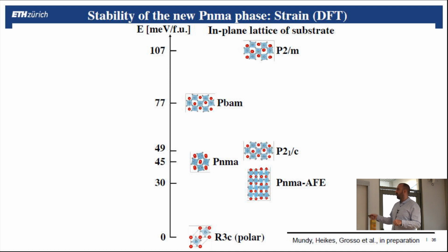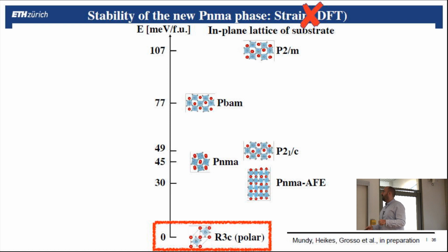And you can see that this is still the lowest energy according to the strain, but there is this phase that is the lowest one above this polar ground state. But that means that the strain is not explaining why this is not happening, but this is happening.